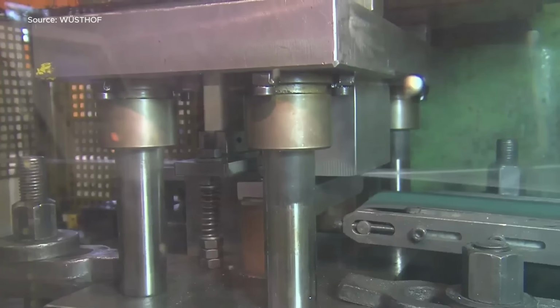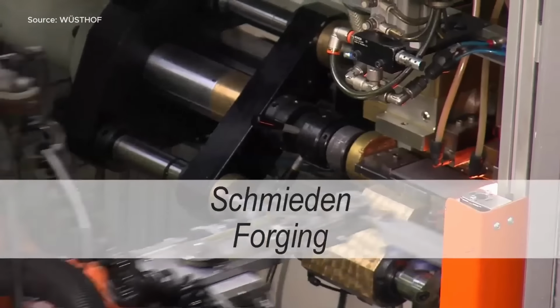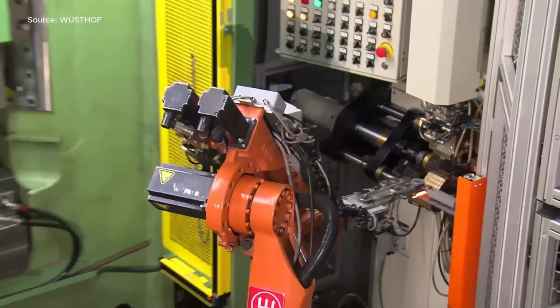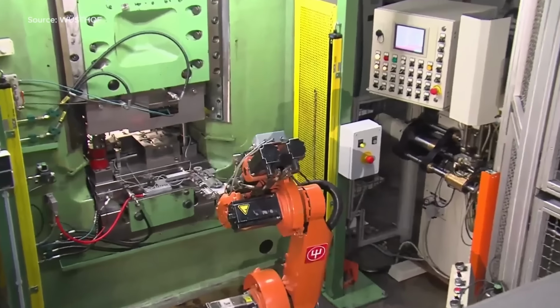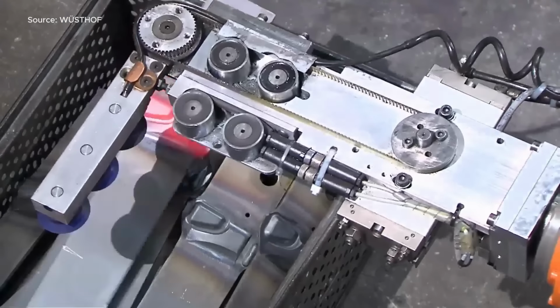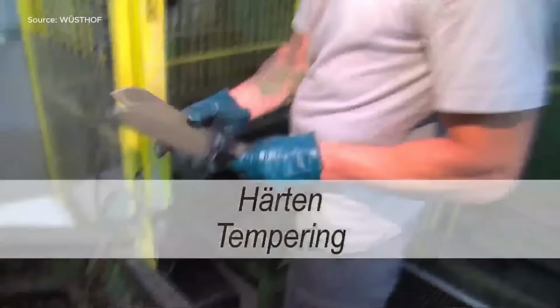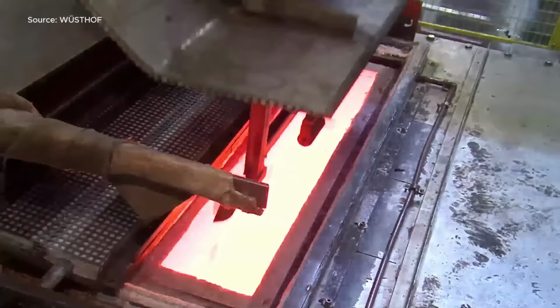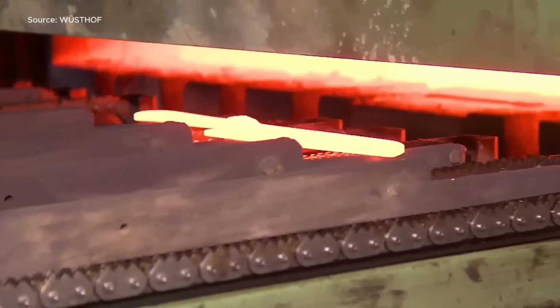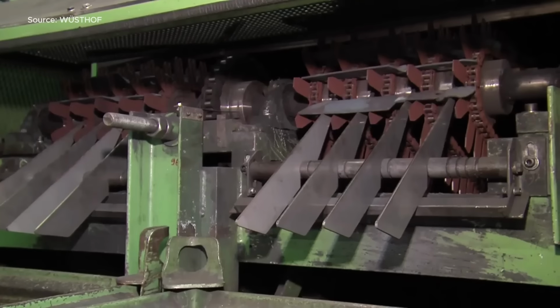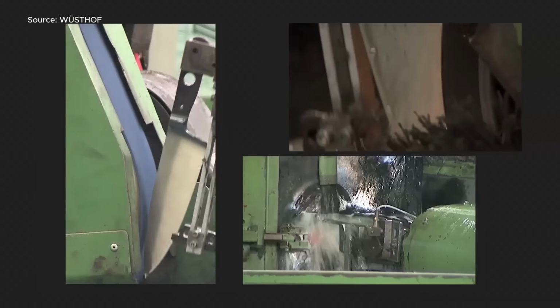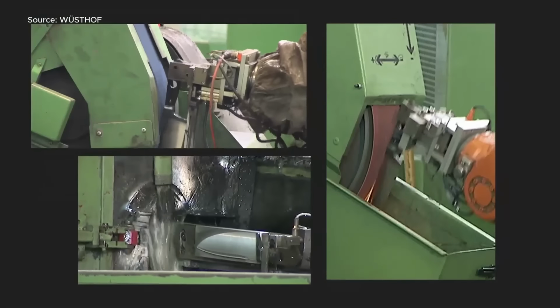Ever held a blade so sharp it feels alive? Here's how that happens. It starts with chromium molybdenum vanadium steel, heated to 1,200 degrees Celsius, then precision forged into shape. A laser cuts the blade, followed by hardening at 1,020 degrees Celsius and tempering at 180 degrees Celsius for that perfect balance of strength and flexibility.